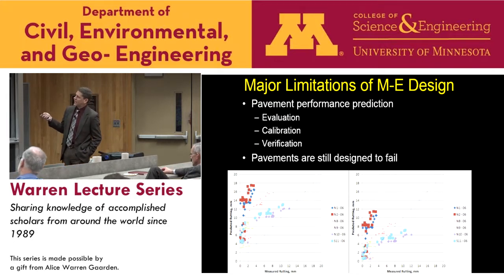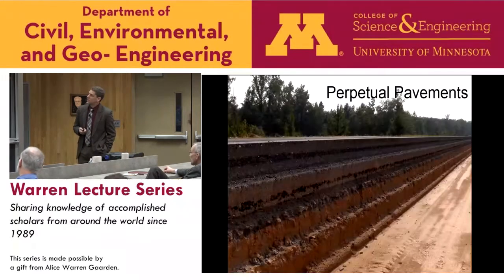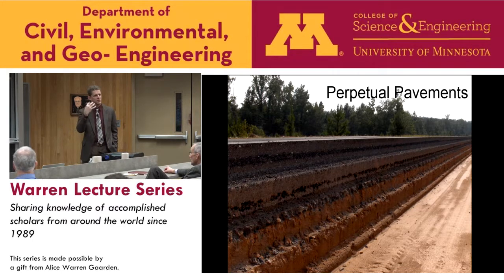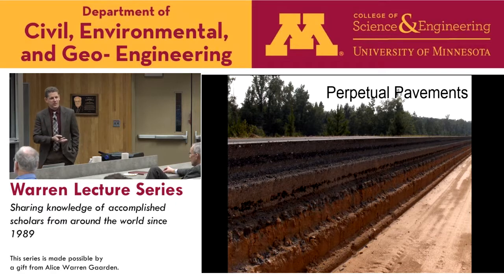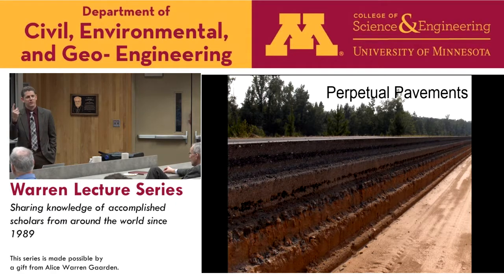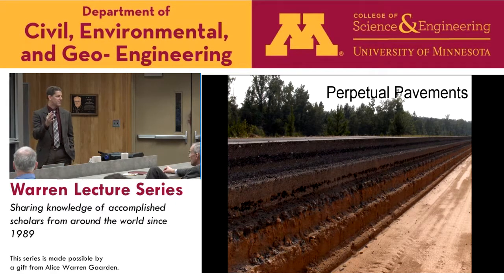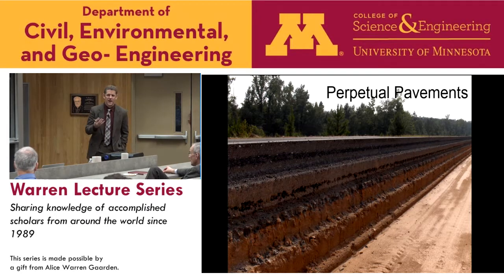And because of that, we are in this kind of endless cycle of having pavements that fail that need to be reconstructed. And it's, as I showed earlier, very expensive to do that. So that leads us then into this idea of perpetual pavements. And the idea being that if we were to, again, think about those stresses and strains, but build the pavement thick enough that we operate below what we call the endurance limit of the materials, we wouldn't have cracks that initiate at the bottom of the pavement and propagate to the surface. When that happens, it's really game over. You can seal it, you can try to overlay it, but it's a Band-Aid. It's not a true fix.